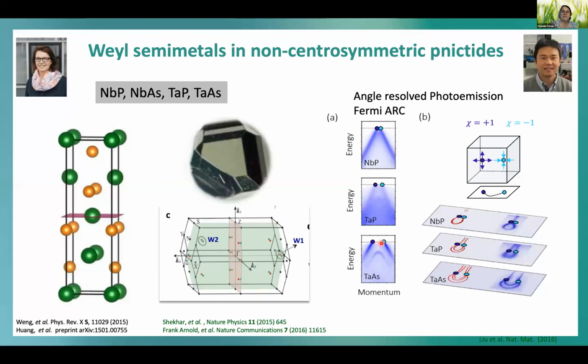But we saw that there was evidence close to the Fermi energy for Weyl points, and the splitting of the bands was enhanced if you made the material heavier - so if you want to say, increasing spin-orbit coupling.